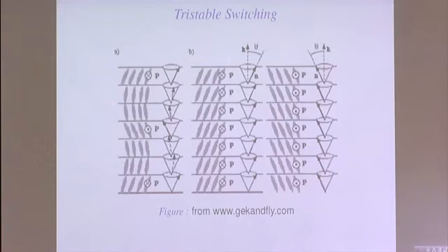So here is the switching. When you don't have any electric field, then molecules have helical patterns. But when you apply an electric field in a certain direction, up or down, they all organize in the same direction. But when you change the direction of the electric field, molecules align in these directions. So in the transition from here to here, you actually go through this state. So this is the famous tristable switching problem.